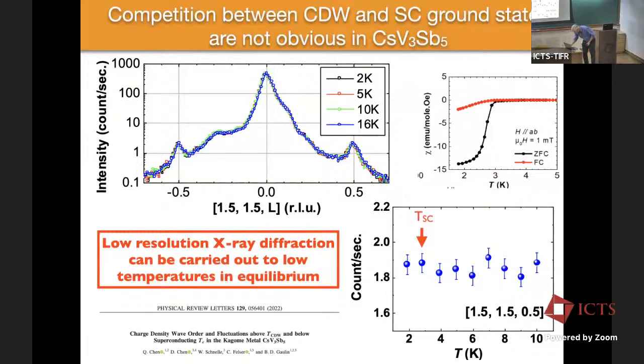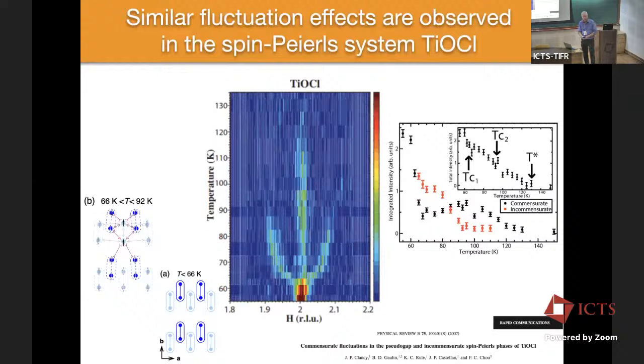I ran out of time, but maybe I'll now cheat the chair and try to sneak in another slide. These are also low resolution measurements done about 15 years ago on an insulating magnet, a two-dimensional insulating magnet that has what's referred to as a spin Peierls phase transition. It's made up of titanium moments, which at low temperatures, it's 3d1, so it's spin 1/2 degrees of freedom that couple antiferromagnetically and form these singlets. So it's like a valence bond state below about 65 Kelvin or so here.